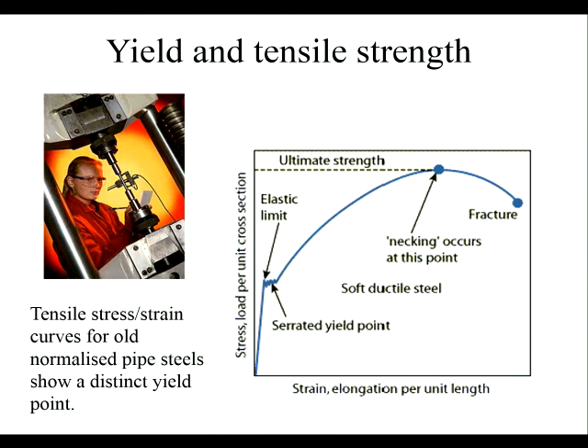So strength. Most people in the industry know about mechanical tests because they will have to do them as proving tests all the time. And the simplest test that you can see here is a standard stress-strain test where we take a metal test piece. In this case, it's a cylindrical bar with some end pieces on it. And we pull it in this test frame, so we stretch it, and we measure the force. And what you can see also on this picture is this thing here is called a clip gauge. So you fix that on, and as you pull it, the clip gauge opens up and it can measure the extension. So you get a force versus extension plot.